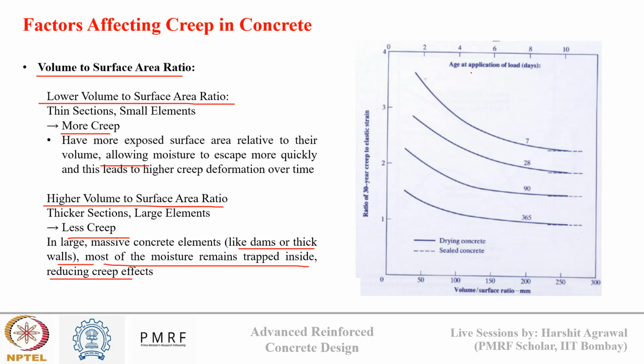And the similar thing is shown in this data also, where you see as the volume to surface area ratio is increasing, the creep effect is decreasing because there's lower surface area which is exposed to the environment. Okay,